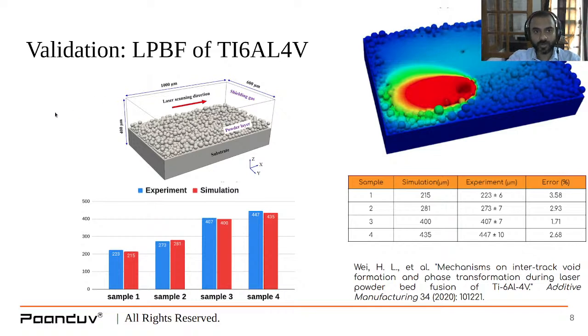Moving on to a complicated case of LPBF, laser powder bed fusion for Ti64, a common alloy. And here also the situation is similar. We have 4 different combinations of laser powers and scan speeds, and they are trying to report the width of the weld pool compared to experiment. Even here the error percentage is reported under 4%, or 3.5% at the maximum, and 1.7% the lowest error possible. So yet again, this is an excellent validation.